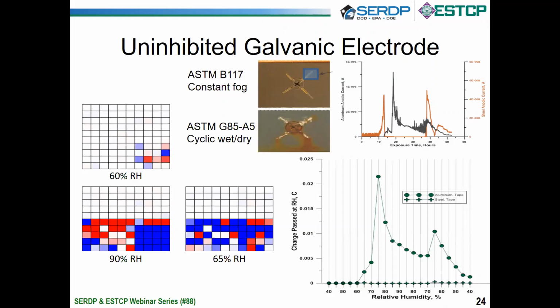One of the things we wanted to figure out was why, and what's driving this. In a lot of the work we've done, we use multi-electrode techniques. Again, please refer to the report and the papers that were written for the discussion of this. Basically, what we had were these 10 by 10 matrices, 100 electrodes, made out of wires that were 250 microns and close packed to each other. In this configuration, and in all these images you see here, these 16 electrodes were made out of steel and the rest were aluminum.